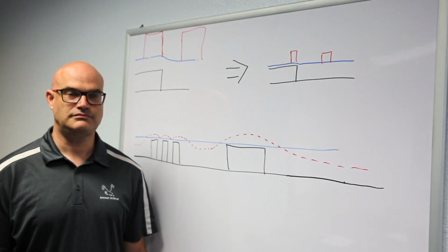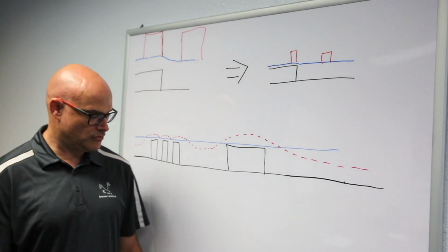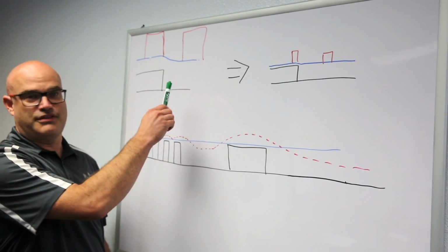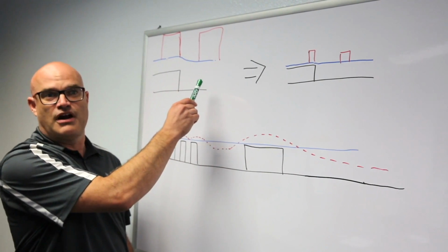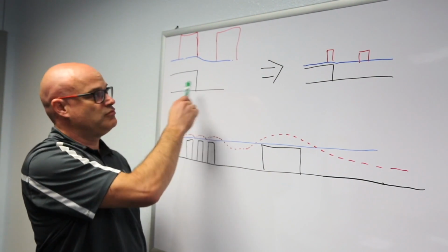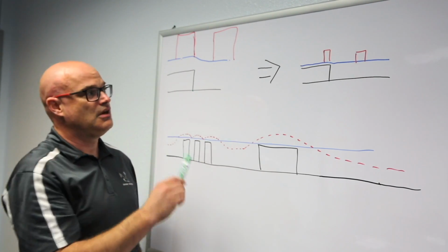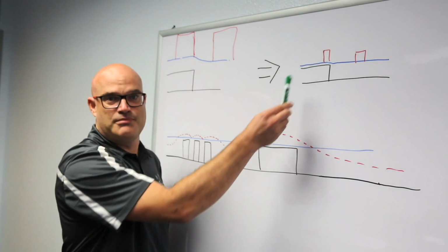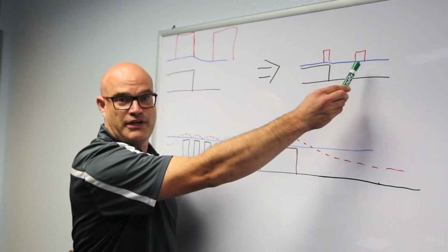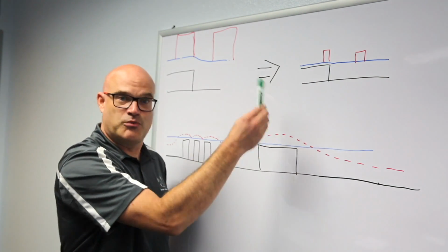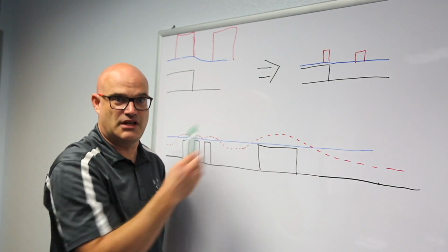Why don't you draw this out for us? Sure. What are we looking at here? Okay, so I drew out a couple scenarios here. Looking at the old days of lithography, we could planarize with a pretty darn thick film. Had big features, we wanted to do etch, we had good etch transfer, no problems. But as things become smaller and more complex, with smaller types of features, you need a thinner film to planarize for etch control, but yet with a smaller film, it's more difficult to planarize. So it becomes a big challenge.